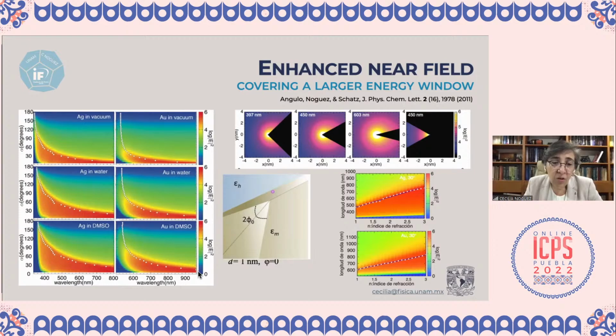And also we can increase up to several orders of magnitude as a function, for example, of the angle. Here, if we take into account how much the energy is increased at a given wavelength because of the response, we can see that for gold and silver, this is gold, in different media like vacuum or water, we can have this increment. These points are where the larger increments are found, and in this way we can not only cover one frequency, but a large energy window, and then be more efficient in plasmonic solar cells, for example.